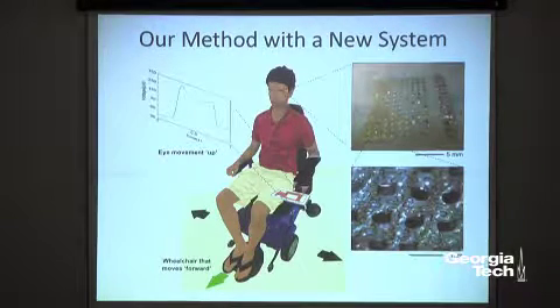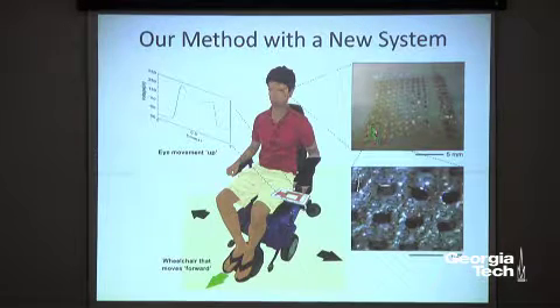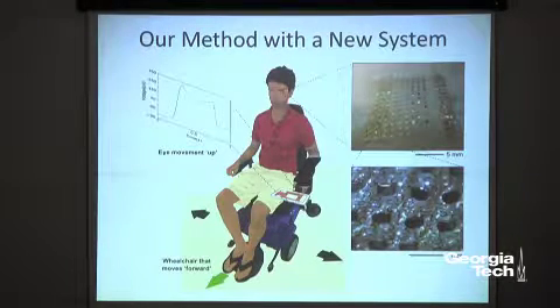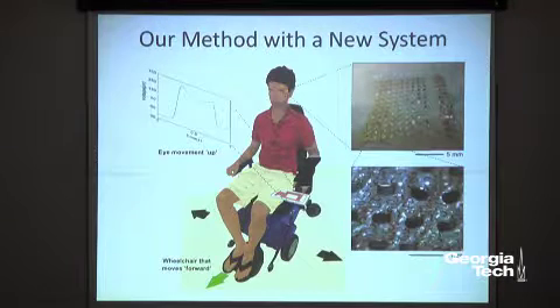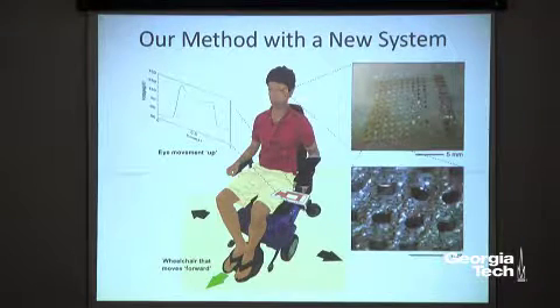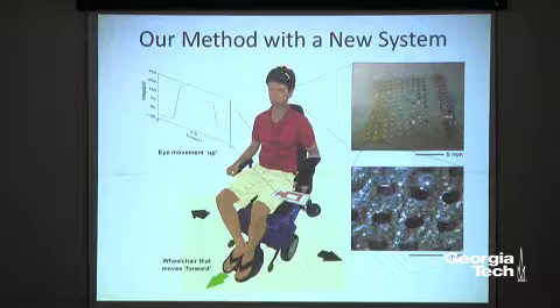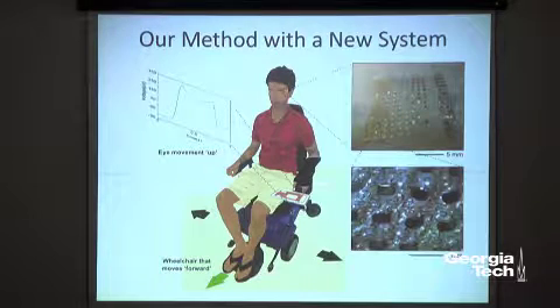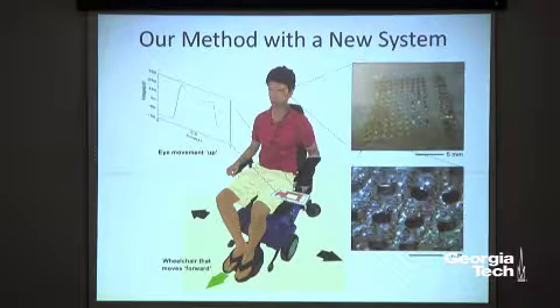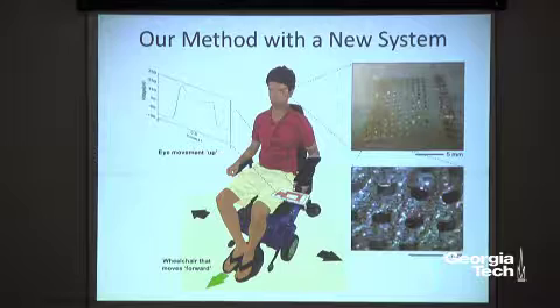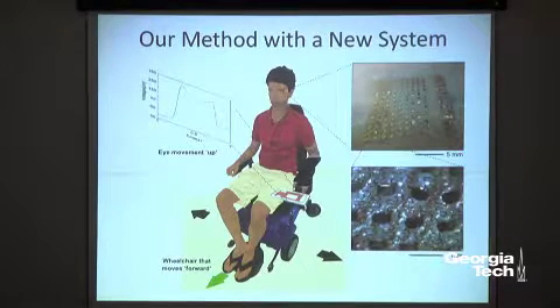Ultra-thin electrode that can be stretchable up to 100%. But if you take a close look, now you have this nice conformal contact without the gel, right? So it's a membrane-based electrode, unobtrusive, and it can measure the eye movement in two different directions, horizontally or vertically. And we record that electropotential, and it's going to be communicating with this data acquisition system on a tablet, and now it's connected to the wheelchair to control it.